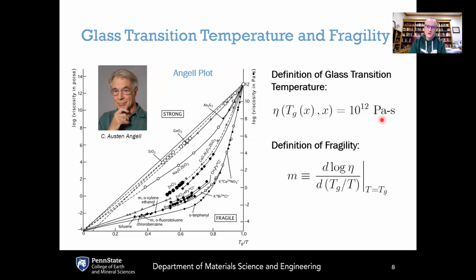He chose 10^12 Pascal seconds because the viscous flow with this value of viscosity occurs on a time scale that is approximately equal to a typical experimental time scale for observing the system in a laboratory. So, in other words, if you have a liquid with a viscosity that is less than 10^12 Pascal seconds, meaning that it's at higher temperatures, then it's flowing fast enough to observe the flow on a typical human timescale.